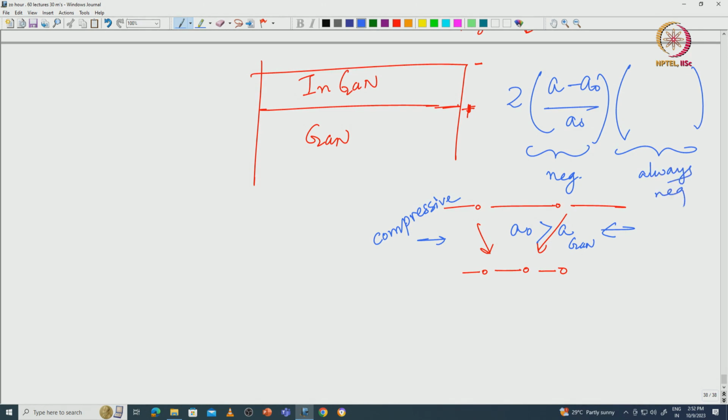Okay. So, essentially what happens is that the piezoelectric polarization for a compressively stressed layer, in this case InGaN on GaN, will give you a positive value, which means the top will be positive. So, I can take the blue color here: the piezoelectric polarization will be positive at the top and negative at the bottom.